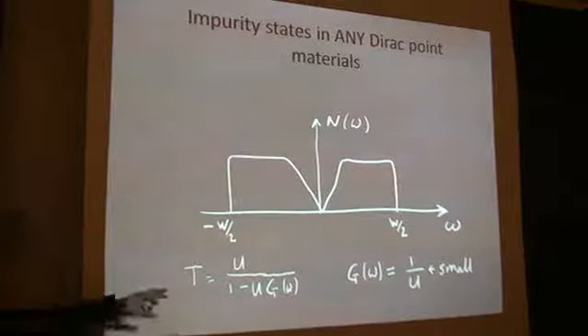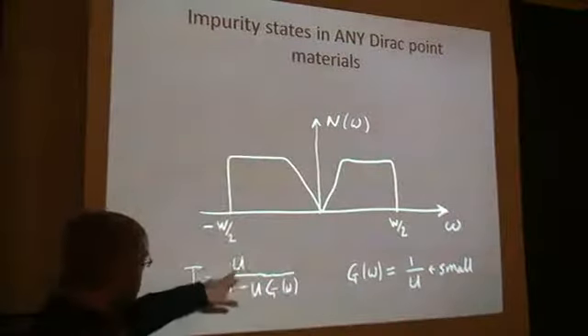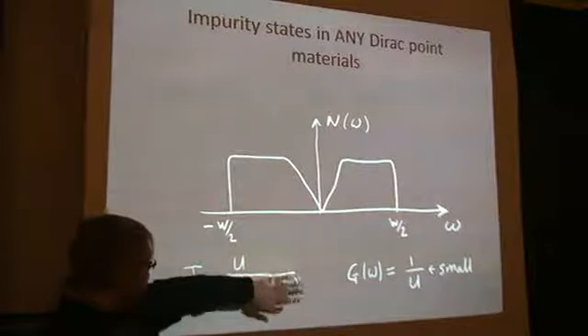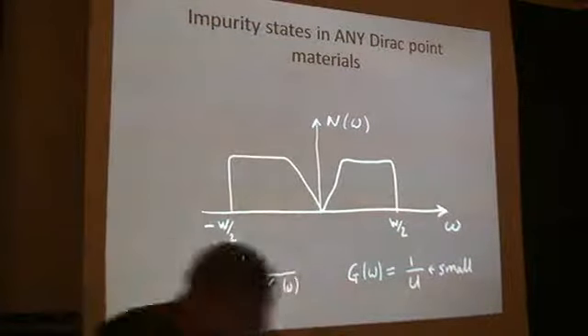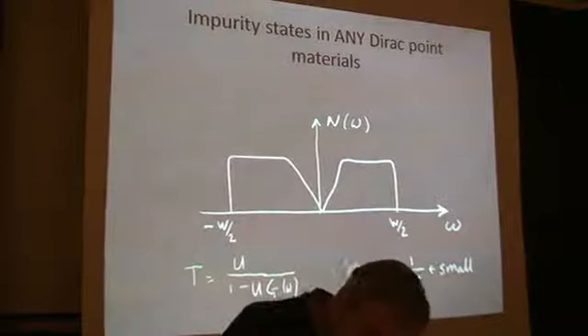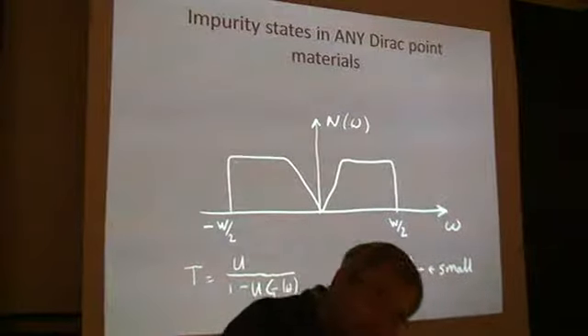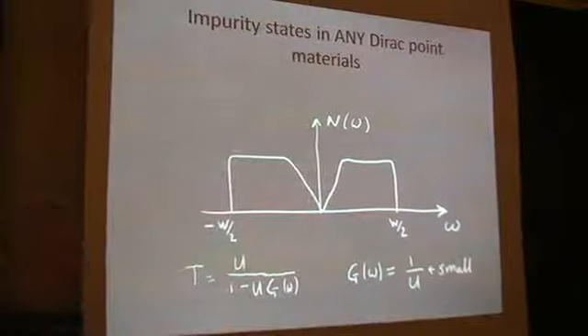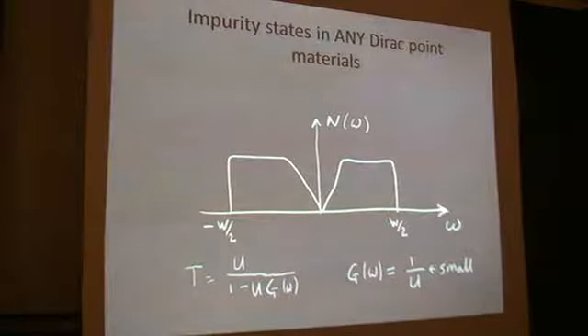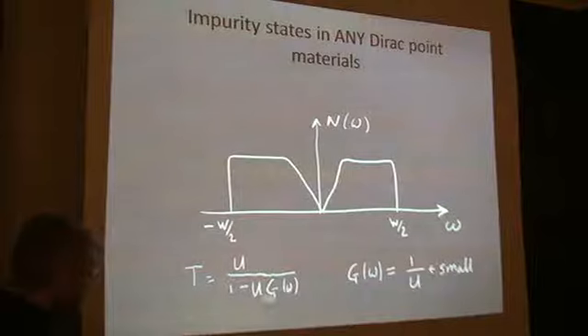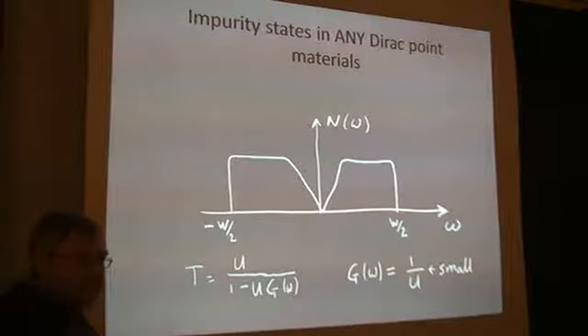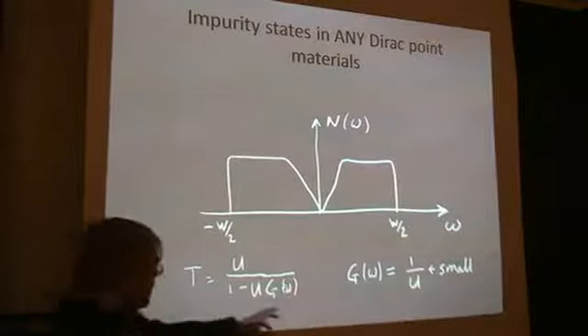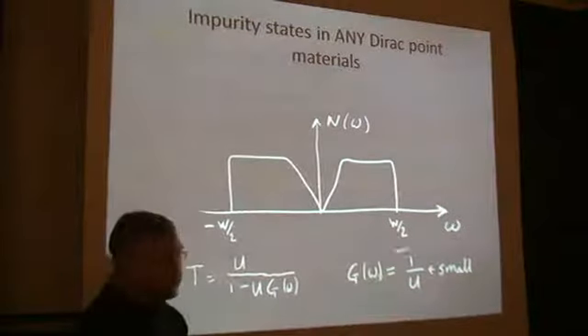And so this Born, basically, if I look at this weak scattering, so like if my potential on one side is U, then in the weak coupling it would be just U. But then if I look at the impurity side, for instance here, and I come in, scatter, and then come out, and then for some reason come back, and I do multiple scatterings. Basically, I will reassemble these multiple scatterings into this Dyson denominator, and in fact, the whole game is actually coming from the denominator. So the blow up of the T matrix, that's how I want to measure the effect of defects, signifies basically the increased dwell time at certain energy, or essentially formation of the bound state near the defect. So the rule is actually, the game would be that I feed in U, and I'm looking for the certain frequency that satisfies this equation, the denominator is 0.